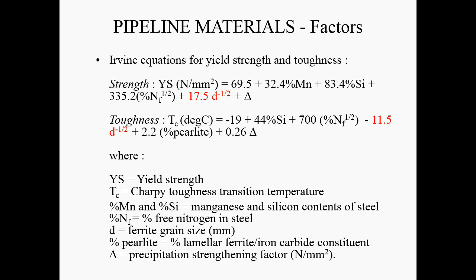So the yield strength is some constant plus a percentage of manganese times another constant, plus a percentage of silicon times another constant, plus the square root of the percentage of free nitrogen times another constant, plus a constant divided by the square root of the grain size, and another constant which is a precipitation strengthening factor. So all of these factors make a difference to strength and toughness.